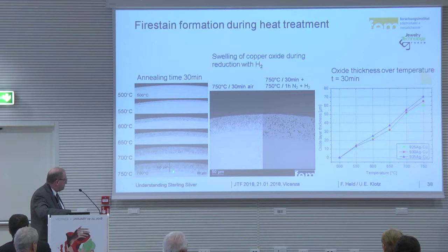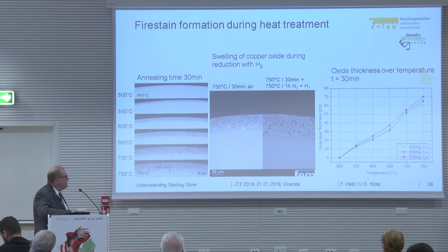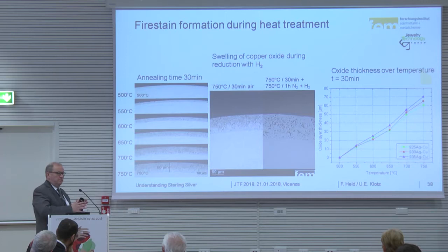If we use only 500 degrees, we know hardness also goes down, but we have no oxidation on the top. We have made this annealing at 750 degrees, 30 minutes under air. We see this thickness of oxidation. Then we make a reduction annealing for 1 hour with forming gas, and we see all the porosity, that this is thicker than this one, only because the silver blows up with pores from the water steam, and so it seems thicker, but it's the same specimen we used.